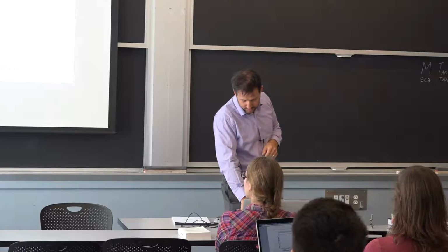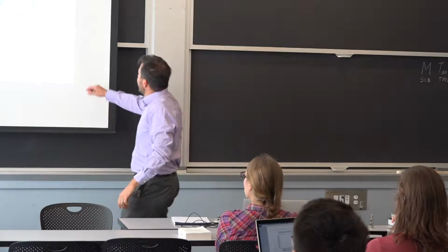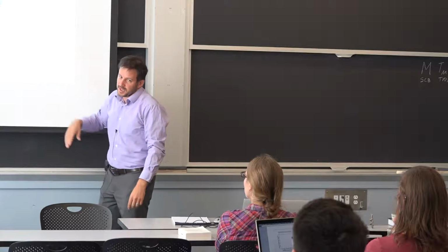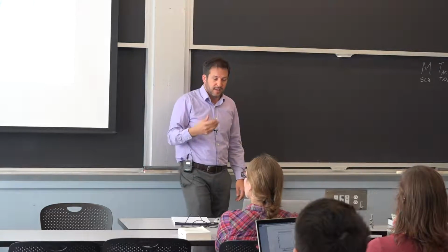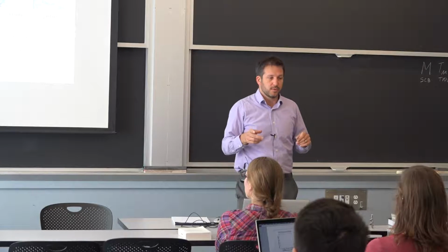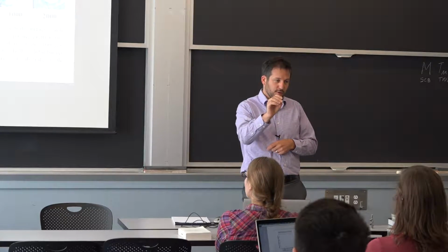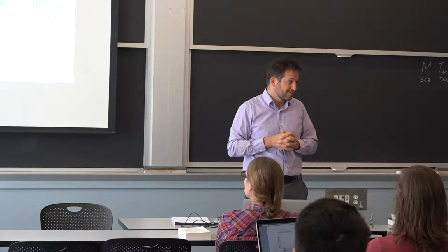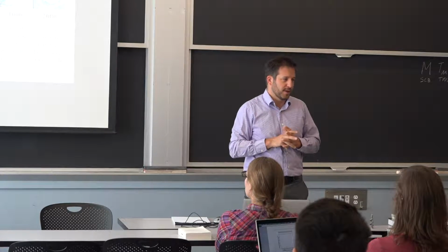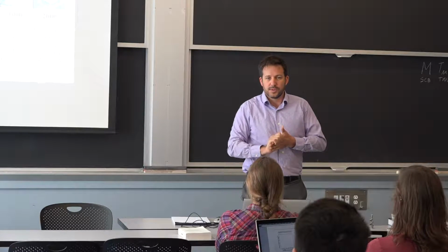The last data point, the rougher sample here, shows a higher heat transfer, but it's not true because it was only at two spots. So if you weigh this one sample here, it actually had less overall heat transfer. It's just because our sensor was at the location of one of the big bulges. So it looked like we were solidifying a lot, when in reality, it wasn't that much.